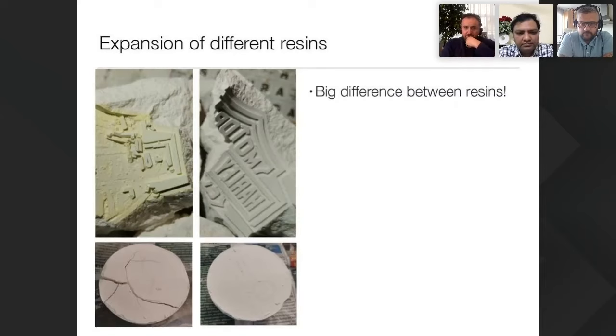By the way, this is a slide I have here which is interesting. We took another resin and one of our castable resins, printed a big part and put it in the investment. We did our burnout cycle, and due to the expansion phenomenon in the investment with that resin, you can see that the whole part on the left, all the details, the investment has cracked and been broken. On the right side, you have a clean burnout. So that's the difference between a good resin and another resin. There are a lot of resins on the market that say they're castable, but according to what? I really don't know when you look at the details.